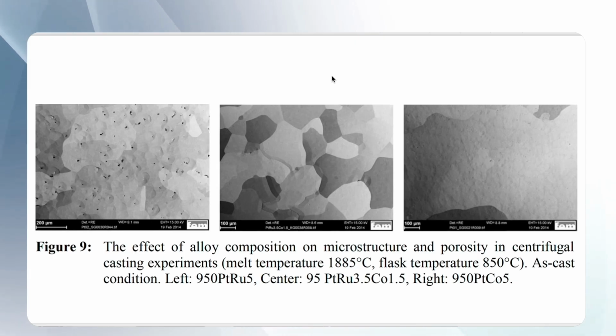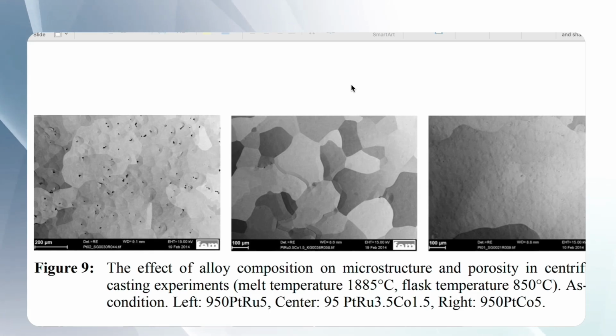But coming back to grain size, we mentioned grain size being one of the attributes that we evaluate for whether an alloy is potential as a casting alloy. And you see in the central image of these three, you see these areas with different gray shades. This is what we call grains, and you can read from the scale - this is in the range that I mentioned, around 100 microns, and this is a very good microstructure. We have a similar grain size with platinum ruthenium, and this is clearly a benefit. Especially if you look to the right, here we see one homogeneous gray region. So the grain size of platinum cobalt is generally larger than that of platinum ruthenium. And therefore, a combination of these two alloys at that time we found could be very interesting.